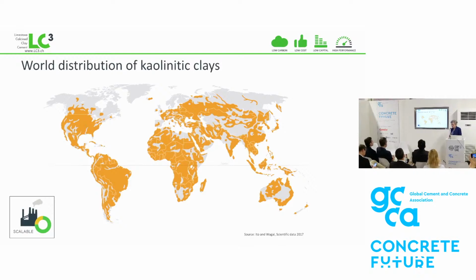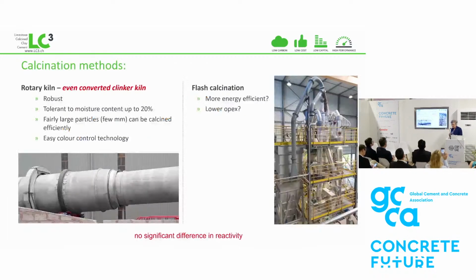And the kind of kaolinitic clays you need are really very widely available just about everywhere. You see this orange color, and even in some regions you don't. You can, as I say, calcine the clay with existing technologies, either a rotary kiln or a flash calciner. You can, most importantly, even do this in an existing clinker kiln. There was an announcement just a couple of days ago from Angola where they're converting 4 kilns to producing calcined clay. So we'll hear more from some of the pioneers.